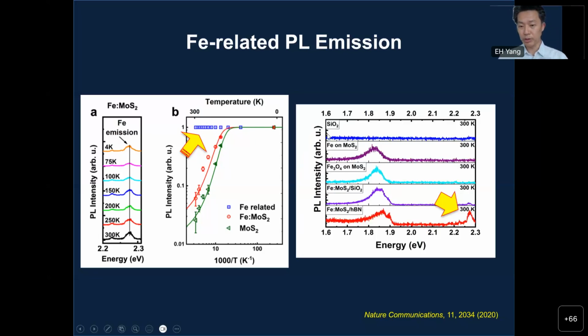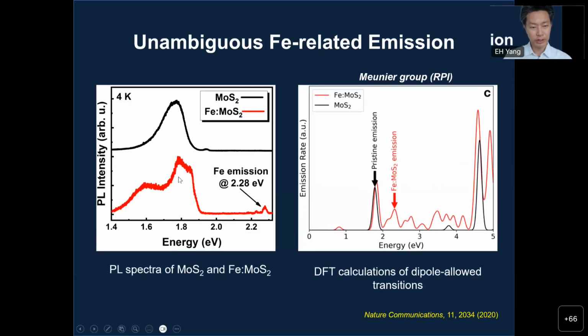So we scrutinized this iron related emission here. We also created control samples to see if one has any related peaks here. Of course, there's none from iron oxide, but you can only see this peak from this iron doped molybdenum sulfide. So that's the exciton emission on the left, about 1.8 eV or so, from the undoped, right? The black and red data. But then you can see this iron related emission at 2.28 eV from the iron doped molybdenum sulfide alone. And then DFT calculations, this is by Meunier at RPI, and these dipole transitions clearly show the iron-related emission from this DFT modeling.